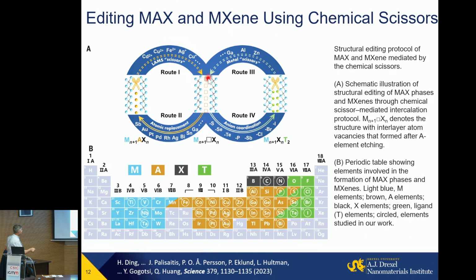And you can also completely remove them, making layers of vacancies, pretty much naked MXene. But after that, you can also put various surface terminations on demand. Chalcogens, halogens, phosphorus, antimony. So basically, we can cut and paste elements into these layered structures. It's a little bit like CRISPR.